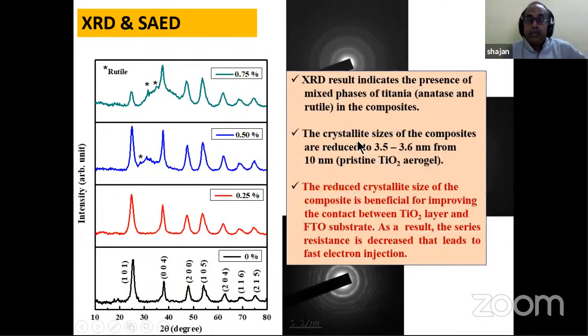You can see this is for pure titanium aerogel, and you can see all the fringes corresponding to each reflection plane of the X-ray diffraction. You can see the rings here. And if you increase that to 0.5%, you can see the difference. And if you still increase to 0.75%, some of the fringes are missing here, and it is showing something different. So what we conclude is that when MOF is added to the aerogels, there is a mixing of phases, the anatase and rutile, in the structure. And you can see the crystallite size is around 3.5 to 3.6 nanometers.